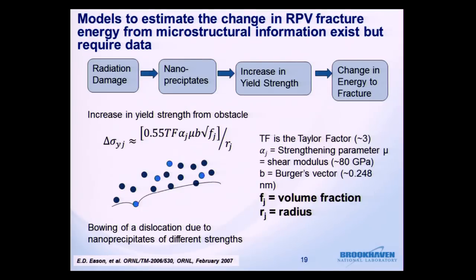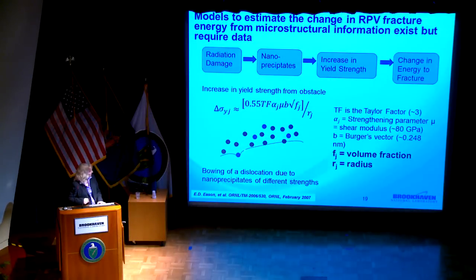So the theory, the model that we have, says the increase in the yield stress is based on the volume fraction and the radius. We need information on the volume fraction and the radius of the nanoprecipitates to estimate the yield strength. These dots are representative of the nanoprecipitates, and this is the dislocation. As the dislocation approaches the nanoprecipitates, it has to bow around the precipitates. Some of them can be cut, some it has to bow around, because these features can be of different strength. But in order to apply the theory, we need data on the volume fraction and the radius of the nanoprecipitates.